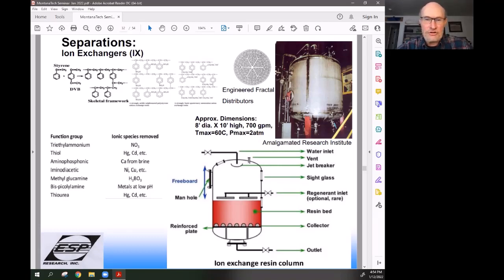The trick is that these swollen polymers are very sensitive to both thermal and pressure gradients, and they tend to compress with any major offsets. Using fractal distributors, you're able to get even pressures going in, even pressure coming out, and you can run huge amounts of fluids through them at very high flow rates and still get good capture of metal ions. This example of an ion exchange column on the right is used in the sugar beet industry, and they have fractals on the top and bottom, and they have the ion exchanger for softening the beet juice in the tank. They're able to run 700-800 gallons a minute through these things. So it's a huge amount of material running through these things. The trick, though, is you have to maintain temperature at a very modest amount, and of course, not have offsets of pressure. So next, please.